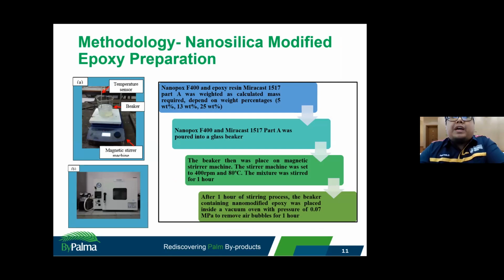And then for nanosilica, we are using Nanopox F400. The name is Nanopox F400. We use it in this study as a modifier for the epoxy. It was supplied by Evonik Industries from Germany in the form of colloidal silica, 40% in epoxy resin. The size is on average about 20 nanometers, and the largest one we found is around 50 nanometers.